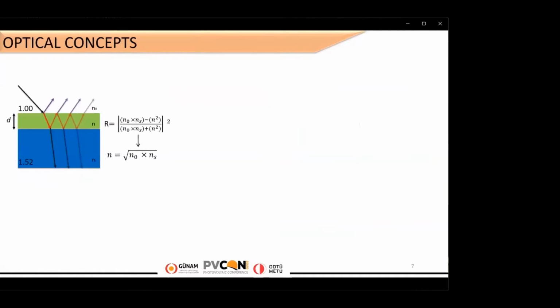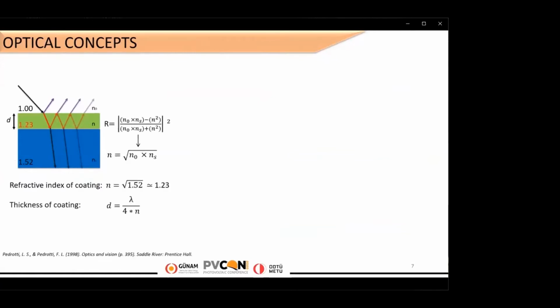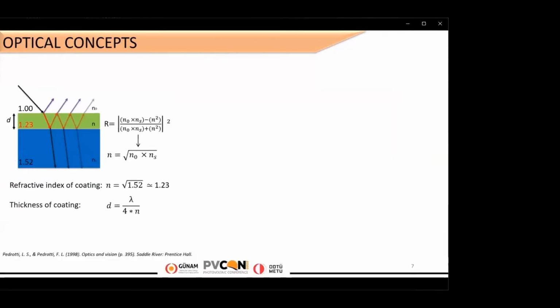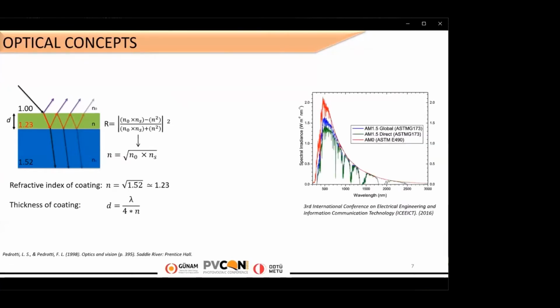I want to give some brief information about optical concepts and some formulas. Basically, a single-side coating system consists of three mediums. These are the air, coating film, and the glass substrate. From the related equations, we know that the ideal refractive index value of the film should be 1.23. And we use the AM spectrum to calculate ideal coating thickness, which is about 100 nanometers. Because the angles and intensities of rays coming from the sun are different at different regions of Earth, for equatorial regions, we use AM 1.5 standard calculations to understand wavelength distribution.